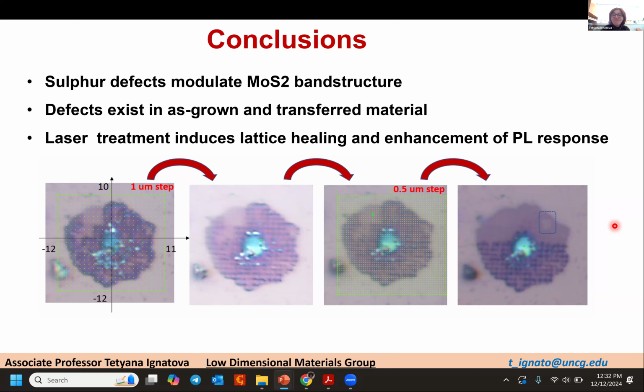Yep. Interesting. And just to follow up on that, do you believe this to be a photocatalyzed effect and not just a localized heating effect? You'd mentioned trying to minimize sample heating. Photocatalyzed effect, yes. Okay, so if you thermally cycle this, you wouldn't expect to see the same amount of healing that you're seeing with the photoirradiation? For this, we have to do it again in argon atmosphere. And we definitely see enhancement of photoluminescence properties after thermal treatment in argon atmosphere. This is true, yes.